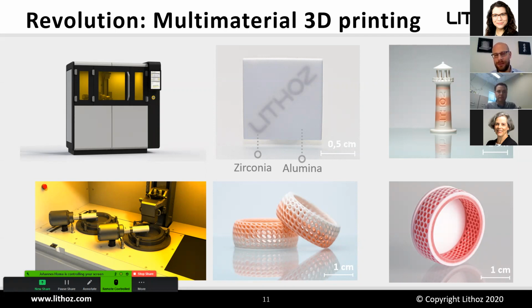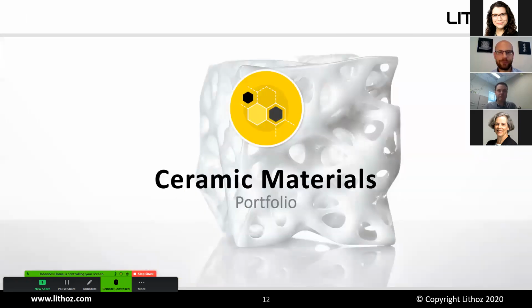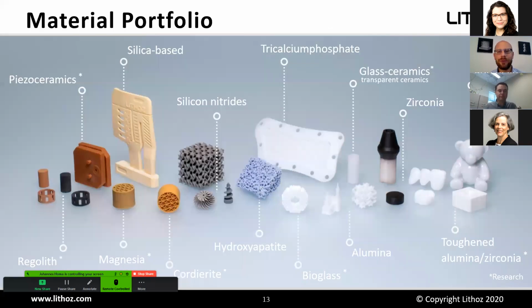also within the same layer. But what we can also do is to combine different materials, as you can see here. So within the same layer, we have combined zirconia and alumina, and we have sintered this to full density. So this is something we are working on, and what we think will also be a big advantage for the ceramic industry.